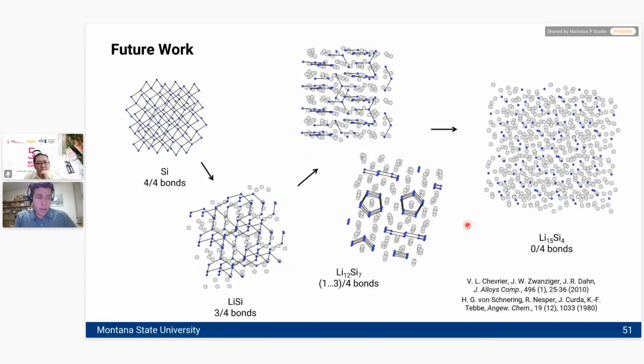As I have a few more minutes, I'm going to show you these crystal structures of how silicon evolves as it gets lithiated all the way up to Li15Si4, to give you an idea of when and where those bonds get broken in the silicon structure. So it undergoes this sort of 1, 2, 3 step process, at least in most silicon anodes. And you can see that even after step 1, the formation of the phase LiSi, we've only got 3 of the 4 bonds remaining that were in the original diamond structure of silicon. In step 2, we now only have 1 to 3 out of the 4 original bonds remaining in each silicon site. That depends on which silicon you are, of course, but all bonds are broken by the time you get to Li15Si4.